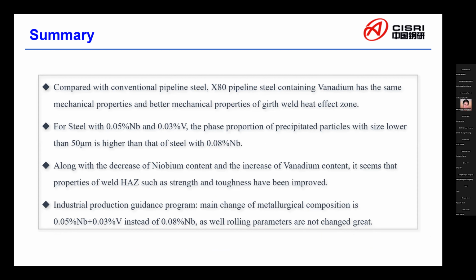In the end, the summary is that compared with conventional pipeline steel, X80 pipeline steel containing vanadium has the same mechanical properties and better mechanical properties of the weld heat affected zone. For steel with 0.05% niobium and 0.03% vanadium, the phase proportion of precipitated particles with size lower than 50 micrometers is higher than that of steel with 0.08% niobium. Along with the decrease of niobium content and the increase of vanadium content, it seems that properties of the weld heat affected zone such as strength and toughness have been improved.